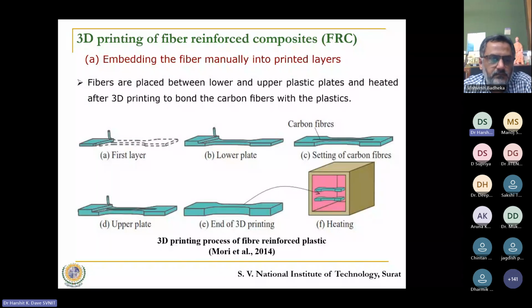The first strategy is a process wherein the embedding of the fiber is carried out manually within two successive printed layers. So by the usual process, what we may attempt to do is print one layer at a time. And after creating one layer, we place the carbon fiber, as you can see in figure C. These carbon fibers or the selected fibers would be placed manually. Of course, continuous fibers would be preferred. And once these are placed, an upper layer is created over these carbon fibers as shown in D. And after repeating this process, we would get a specific part as shown in figure E.